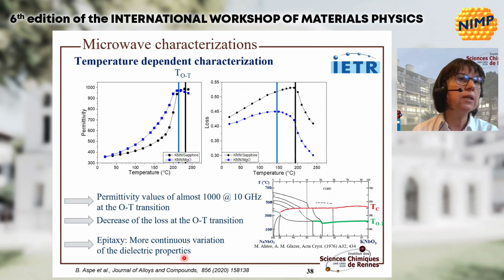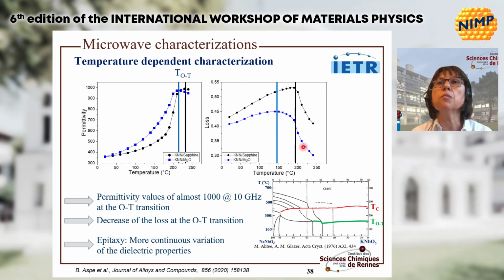What about the behavior in temperature? You can have a look here on the evolution of the permittivity versus the temperature for the two ferroelectric phases, orthorhombic and tetragonal. This is a pseudomorphic transition measured on the two samples, on sapphire in black and on MgO in blue. We can see that a permittivity of almost 1,000 has been obtained at 10 gigahertz in the neighborhood of the transition, a decrease of the losses, and a transition that is more continuous on magnesium oxide.